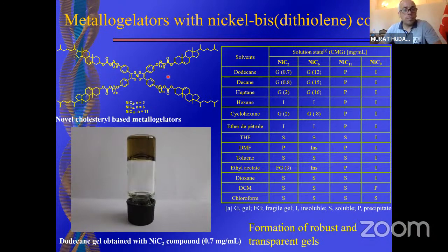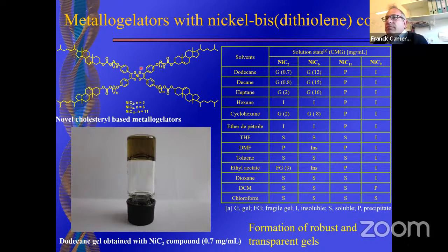Yeah. So we developed the design of these molecules by introducing this cholesterol function, which is well known to impart gelation properties. And we managed here to obtain gels, really strong gels, with a low quantity of gelating agents.